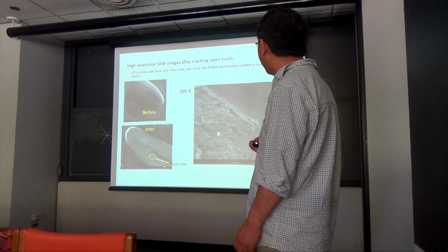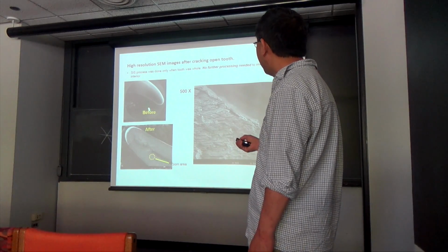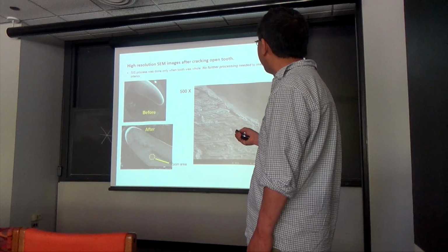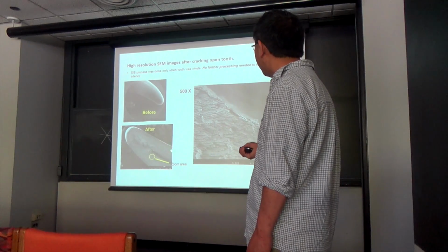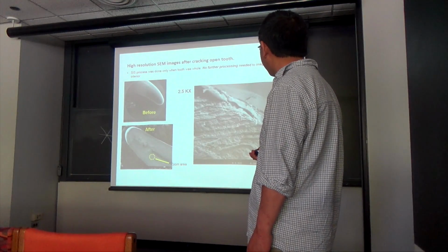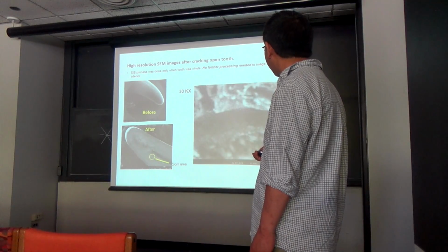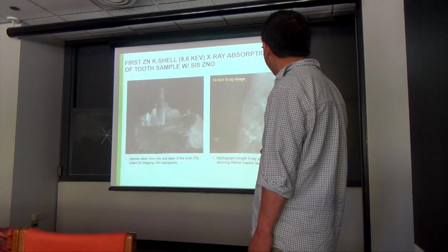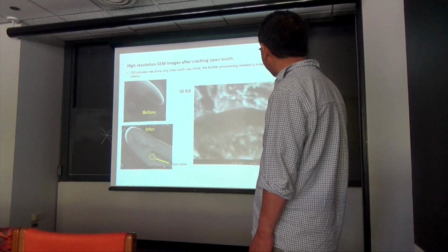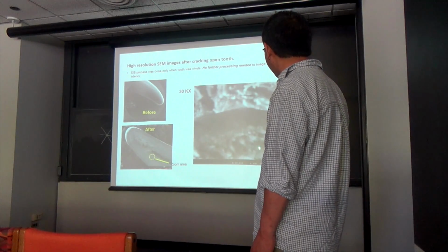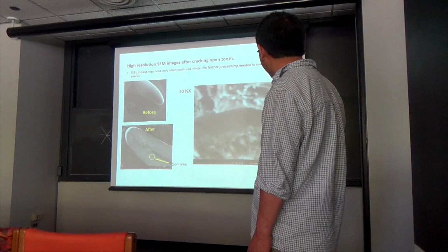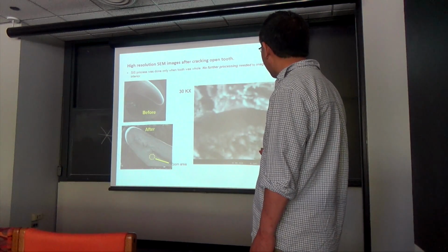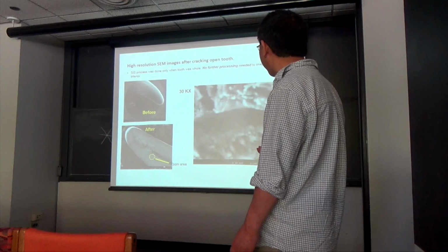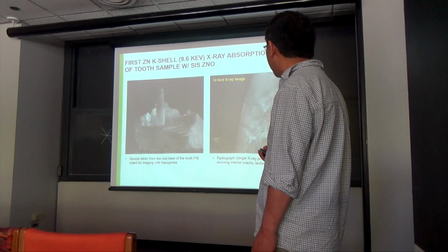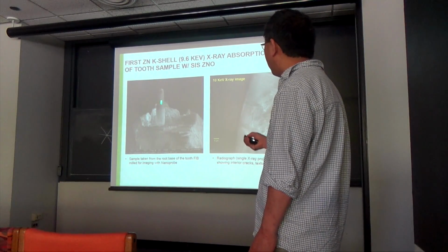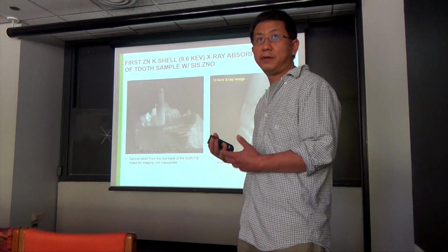But the example I'm giving here is just a tooth structure. And you can see these are high-resolution SEM images of the tooth, showing different features as you gradually zoom in. If you turn off the light, you can even see better. You can actually see very fine structures down to less than 100 nanometers. The bar here is 100 nanometers. This is very difficult to achieve in a conventional SEM. But coupling with the X-ray, you can see even better.